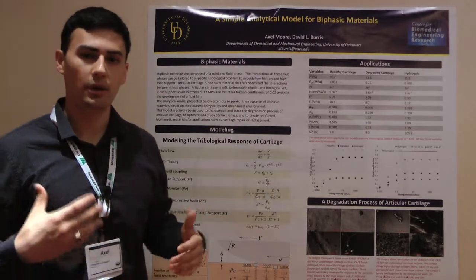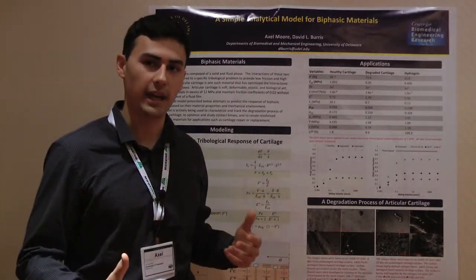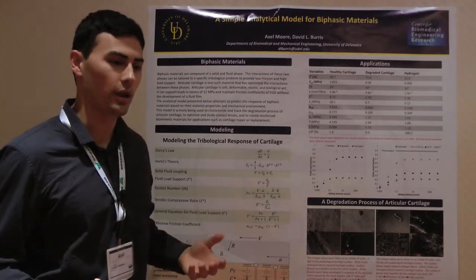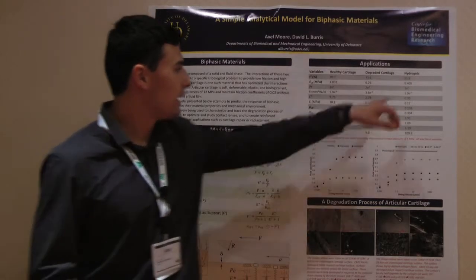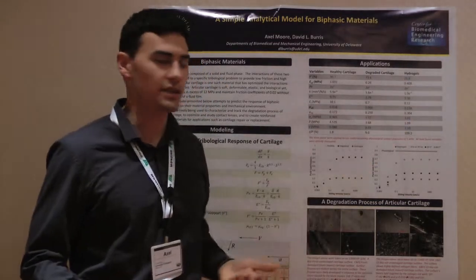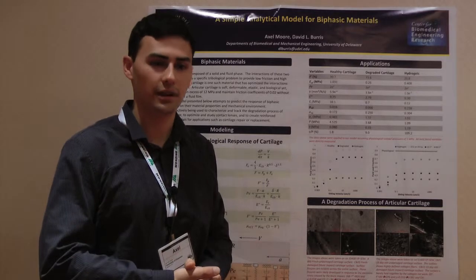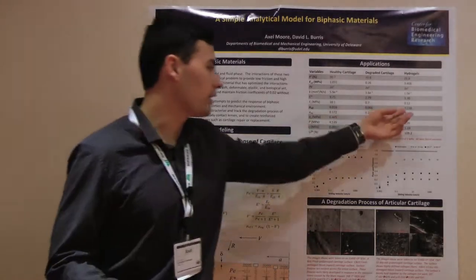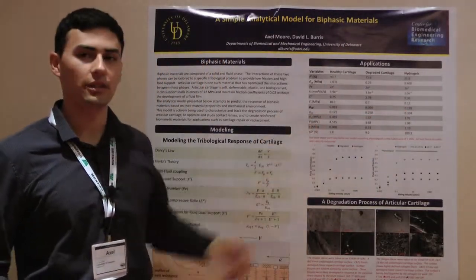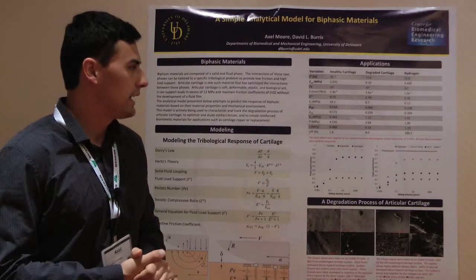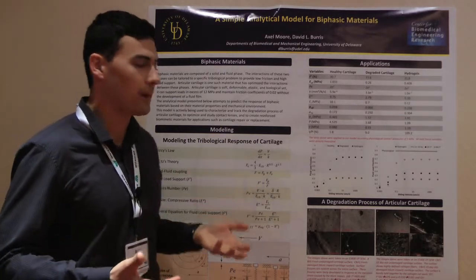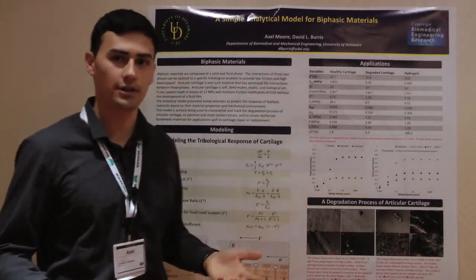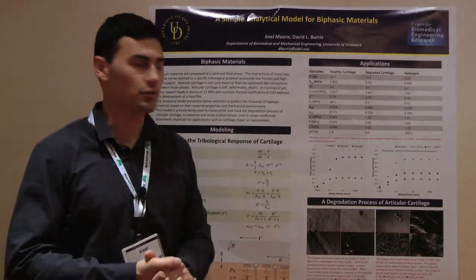Looking at hydrogels — the material we want to design or tailor to cartilage mechanics — right now they're nowhere near the needed parameters. They don't substantially support load through fluid pressurization. Fluid pressurization can support only 21.8% of the load in typical hydrogels, such as contact lenses, and friction coefficients are around 0.2 — a whole order of magnitude above healthy cartilage. We believe that by boosting the fluid load support up to 90%, we'll effectively reduce the friction coefficient to physiological levels.